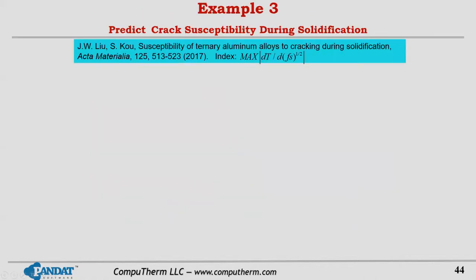Now I have a third example, used to predict crack susceptibility during solidification. In 2017, Liu and co-authors published a paper in Acta Materialia proposing an index that can be used to estimate crack possibility for different alloy compositions in aluminum alloys.